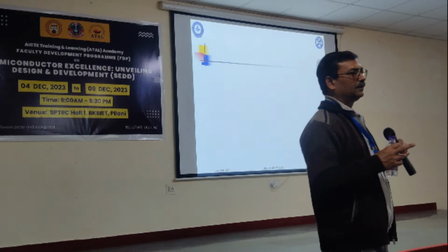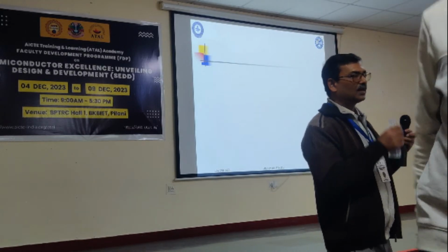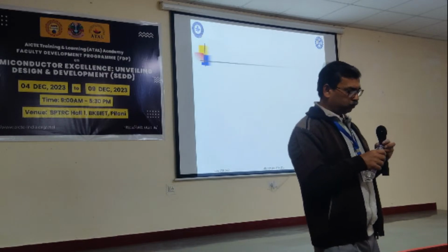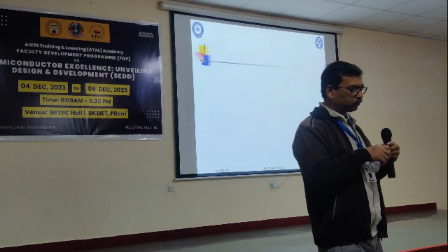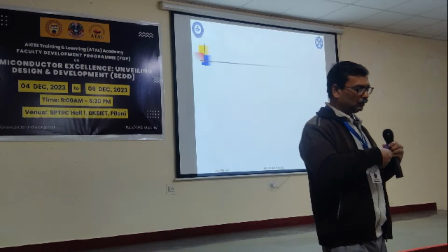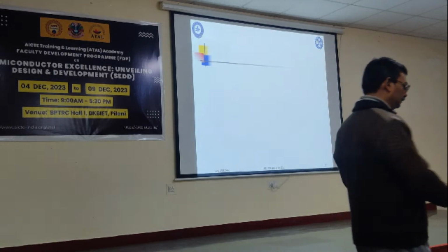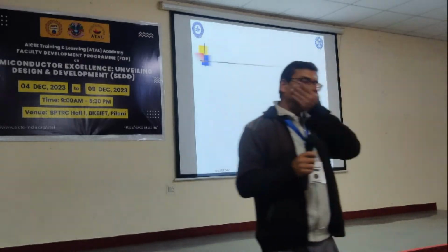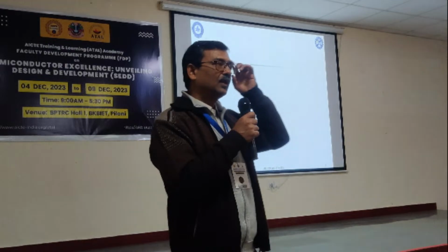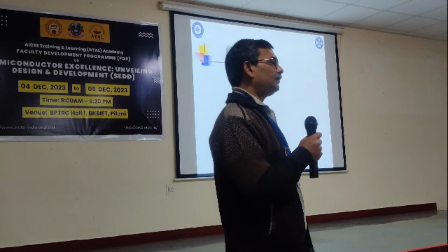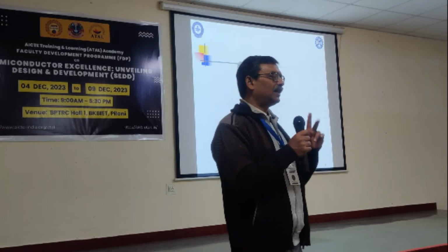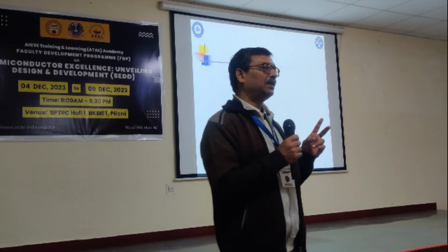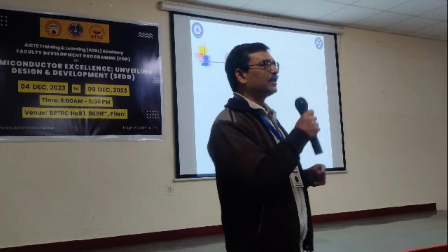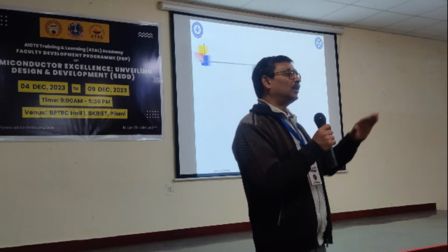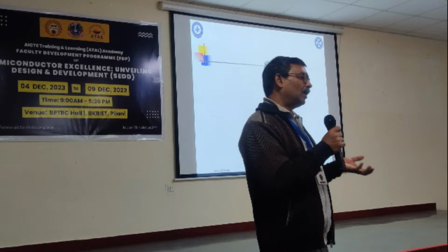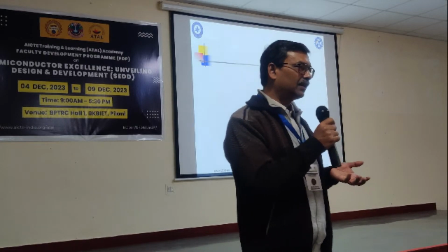Suppose we want to grow GaN on a sapphire surface. So there is no epi layer generated in between, meaning we directly grow GaN on a sapphire surface. When you grow the material, there are two terms. One is deposition, another is epi-layer formation. Epi-layer formation means that with the deposition, we need to fulfill the condition of lattice matching.